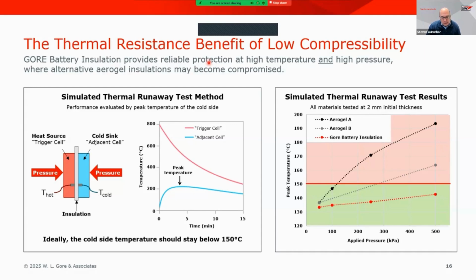And so when you can deploy half the thickness of the aerogel pad, that in essence would be half the weight. And so for those applications that do require very low weight, such as aerospace and defense or even automotive applications, we believe that we can be a very interesting solution because we can deploy it at a lower thickness of the material with a comparable density.